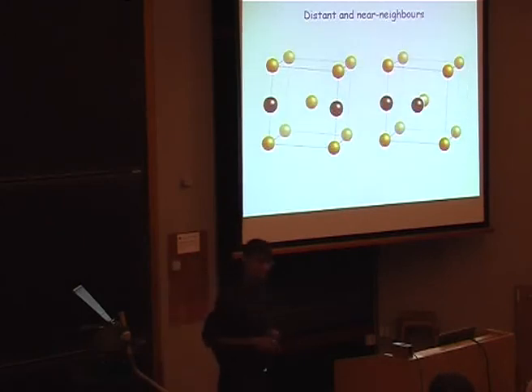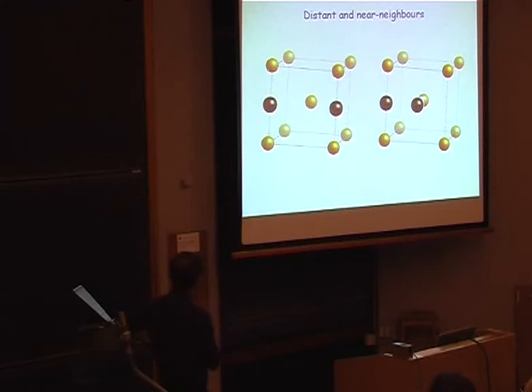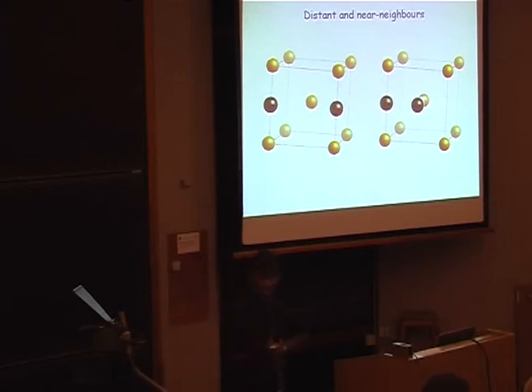So you can solve this using the sort of work you do in this department, first principles calculation. So here is a unit cell of iron, body-centered cubic iron. These two carbon atoms are placed in the second nearest neighbor sites, where I expect the interaction to be slightly attractive, because if it wasn't attractive, you would never get the tetragonal martensite. However, if I put them in the nearest positions, then there should be a strongly repulsive force between those carbon atoms.